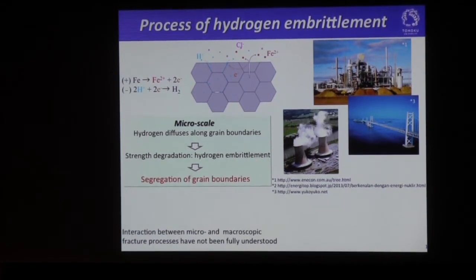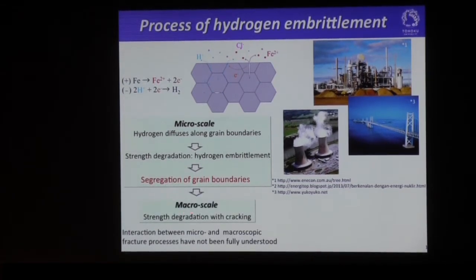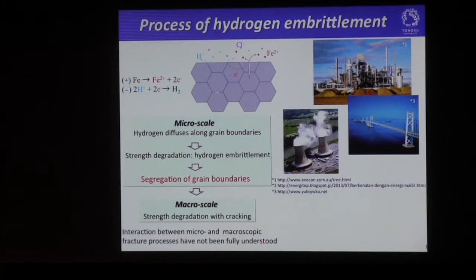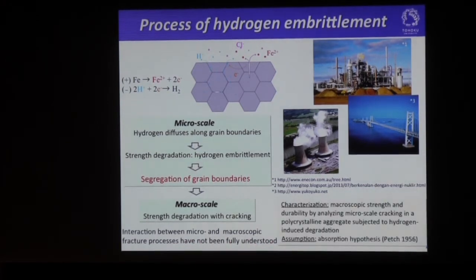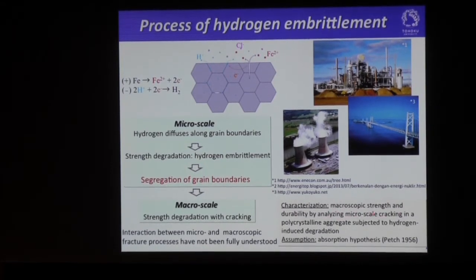Which eventually causes the segregation of the grain boundaries. As a result, the macroscale strength also decreases with cracking. But unfortunately, the interaction between the micro and macroscopic fracture processes has not been fully understood yet. So I'd like to characterize the macroscopic strength and durability by analyzing the microscale cracking in a polycrystalline aggregate, which is subjected to the hydrogen-induced degradation. For that purpose, I assumed the absorption hypothesis as a mechanism of the hydrogen embrittlement.